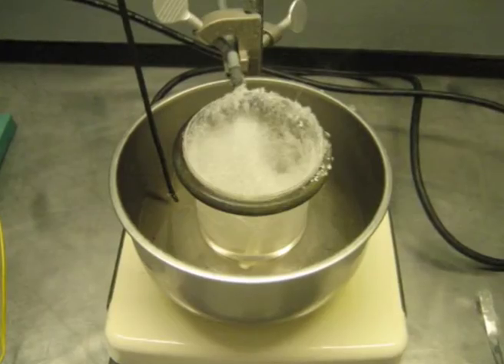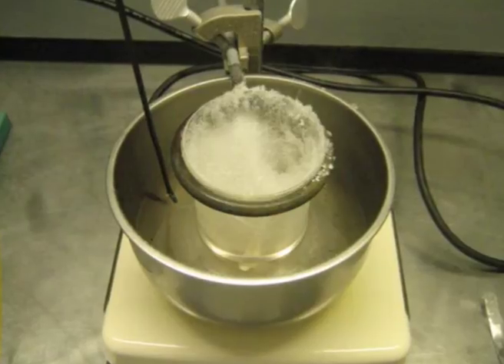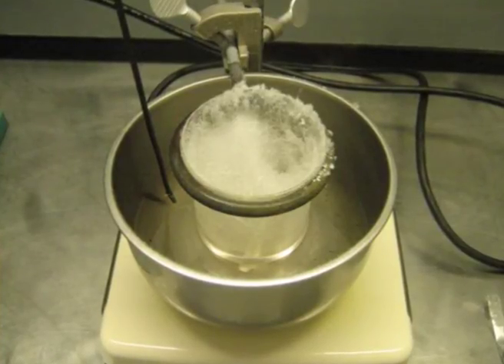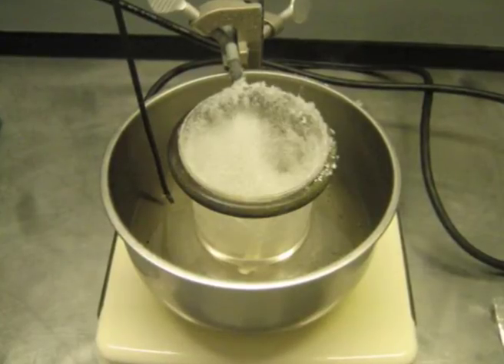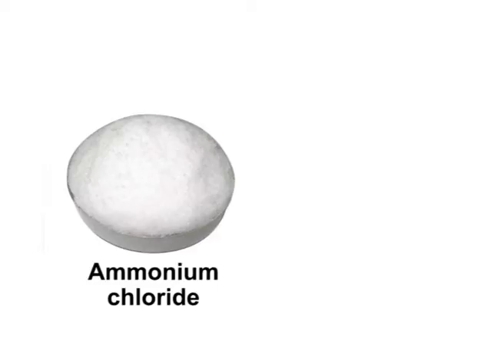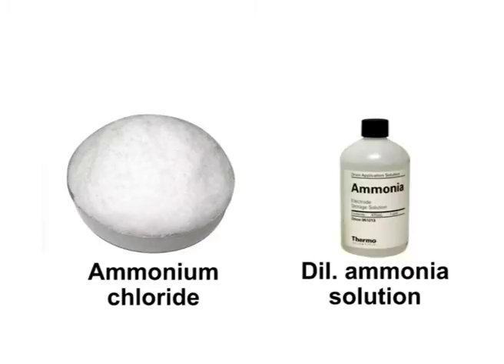Add a little more acid and evaporate the contents to dryness on a water bath. Cool it, dissolve in 20 ml of water, boil and filter. To the filtrate, add about 2 grams of ammonium chloride and 5 ml of dilute ammonia solution. Remove the precipitate which is formed, if any, by filtration. To the filtrate, add sodium phosphate. A white crystalline precipitate of magnesium ammonium phosphate is formed. Second test: it yields the reaction characteristic of silicates.